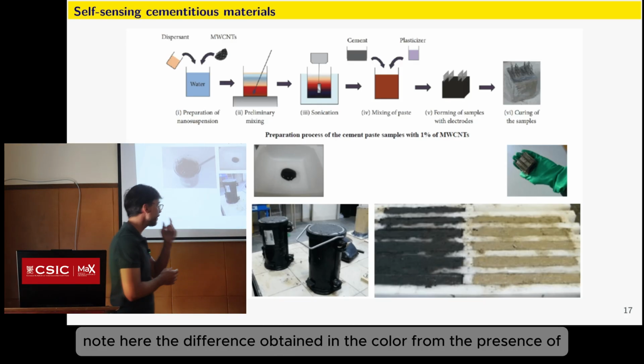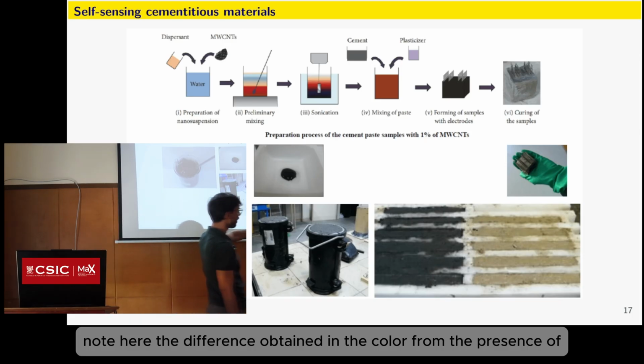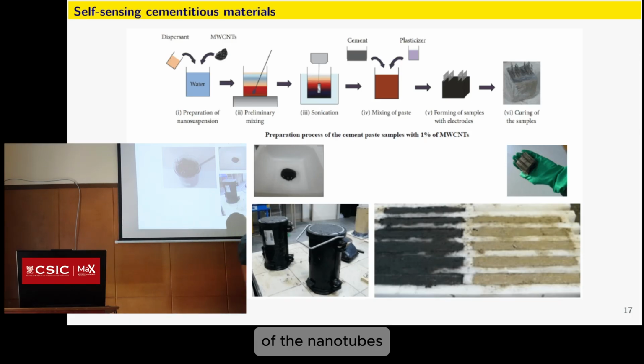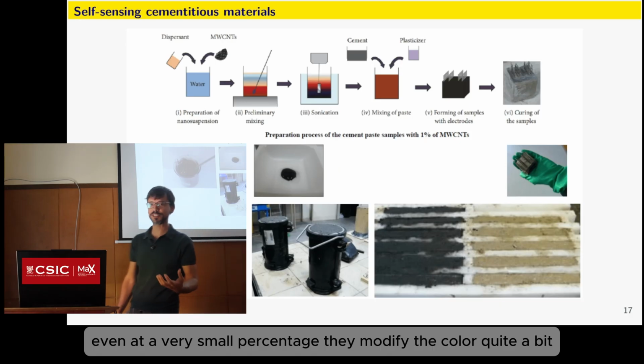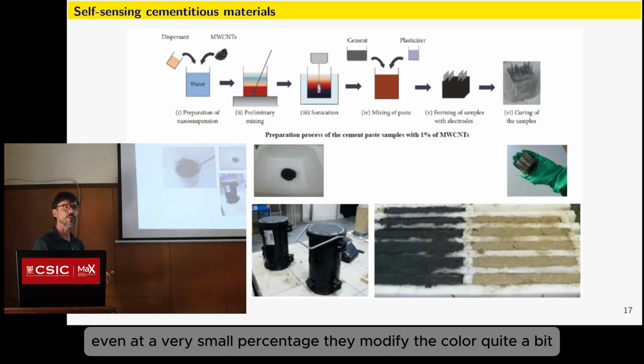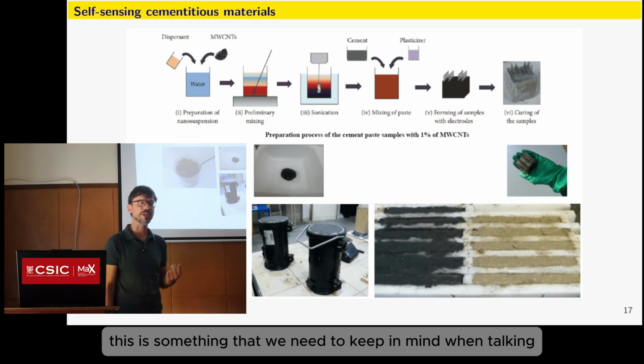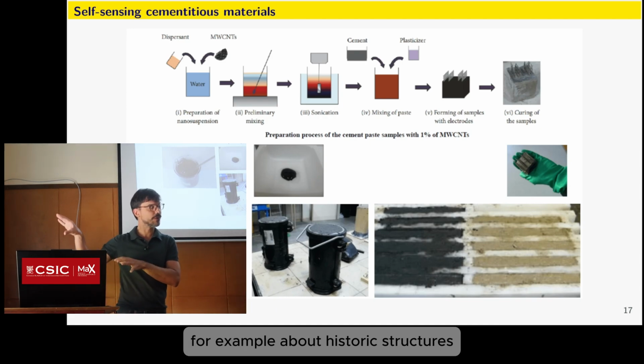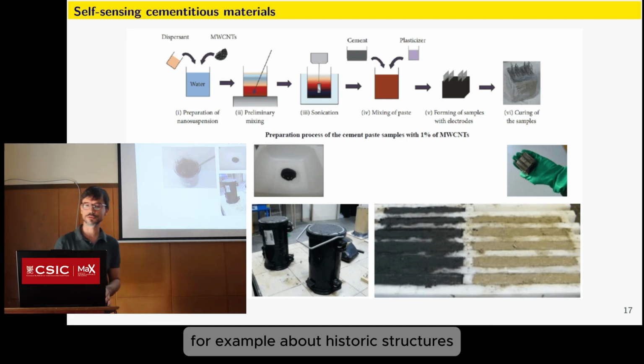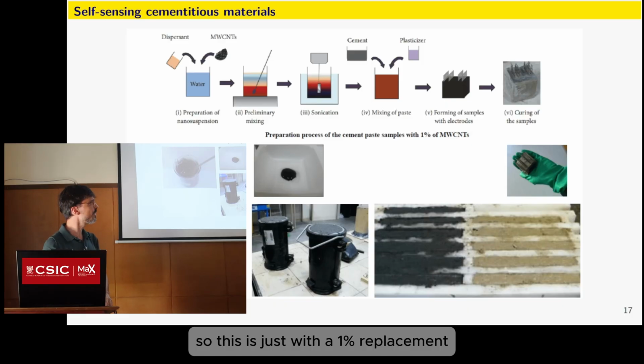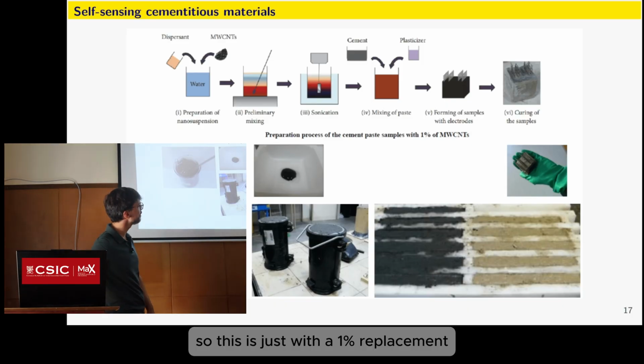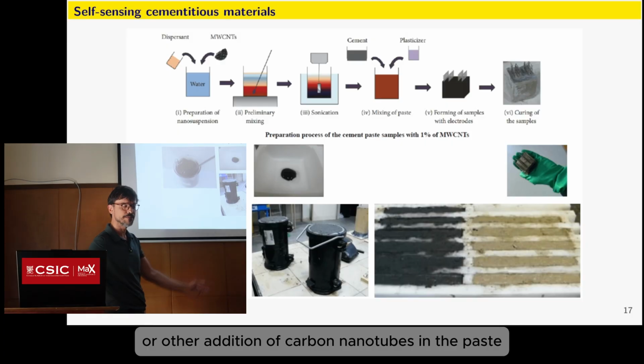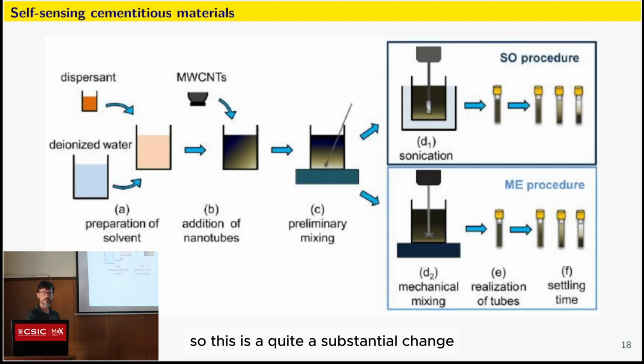Note here the difference obtained in the color from the presence of the nanotubes. Even at a very small percentage, they modify the color quite a bit. This is something that we need to keep in mind when talking, for example, about historic structures. So this is just with a 1% replacement, or rather addition, of carbon nanotubes in the paste. So this is quite a substantial change.